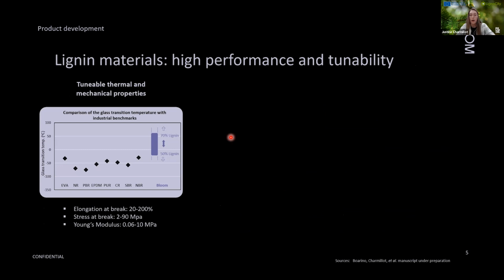So depending on the lignin content, here is the glass transition temperature of typical materials, elastomers, and here is what we can obtain by varying the lignin content. You see this is a wide range, and same for the elongation at break, stress at break, and Young's modulus. We have a wide range to work with, so this allows us to tune the materials depending on the application, and this is an advantage because we can go really high in the lignin content, and also by changing the crosslinker, we can change the property.